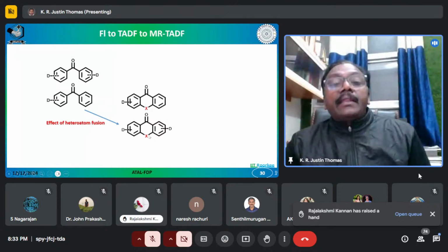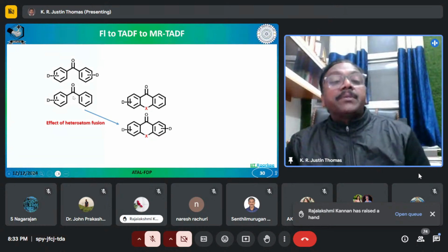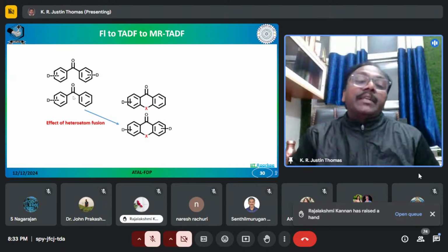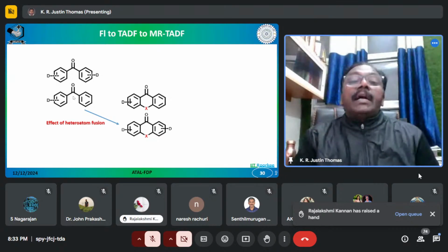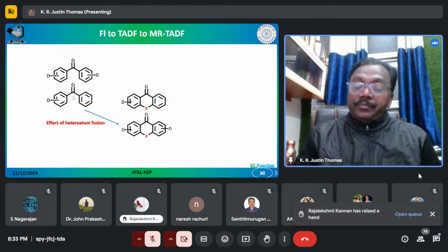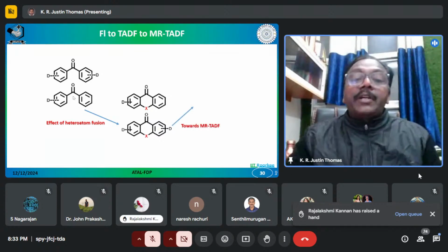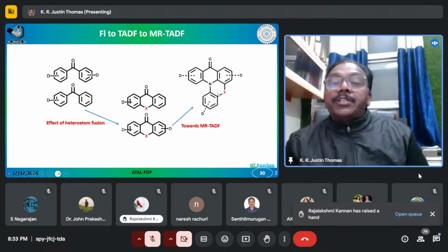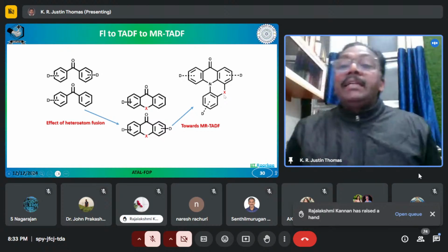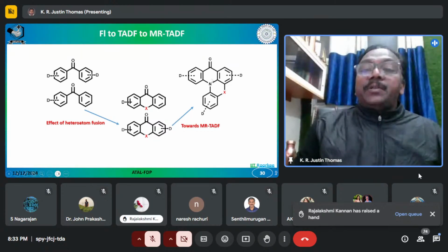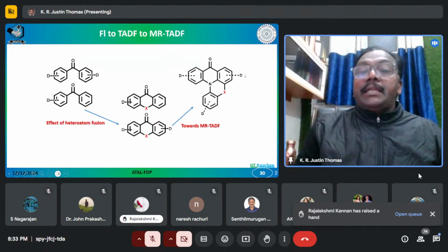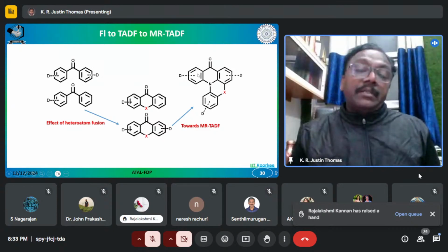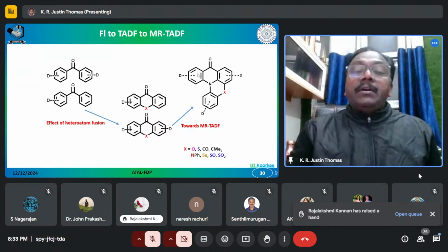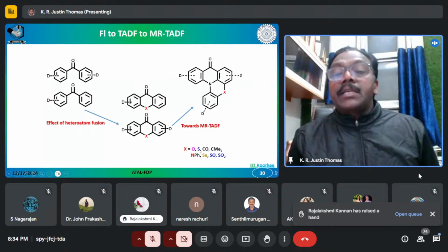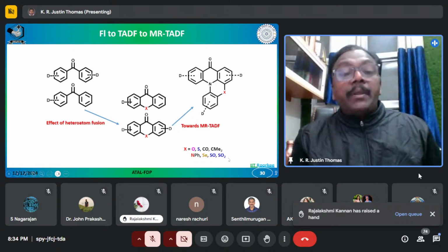The good property that you are retaining in this molecule is the spin orbit coupling that is taking place in benzophenone. Now, by fusing, you are adding an additional dimension to the molecule. Now the molecule becomes a rigid donor, rigid molecule also. You can take a system where you have X equal to N-phenyl, and then you can have a further fusion. So now what you have done here is an acceptor here and a donor here, and an additional fusion leads to an MR-TADF. That means that alternate atoms are now becoming donor and acceptor, inheriting HOMO and LUMO respectively. You can have the X group as anything like oxygen, sulfur, carbonyl, CMe2, NPh, selenium, SO and SO2. A lot of variations have been found.